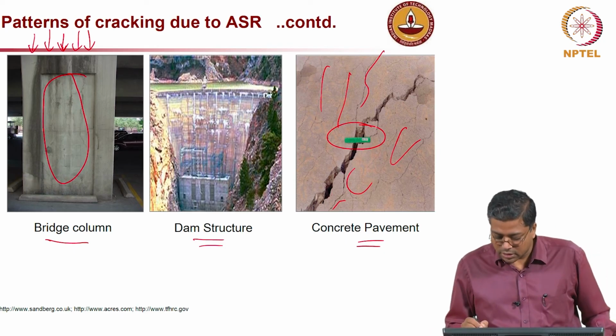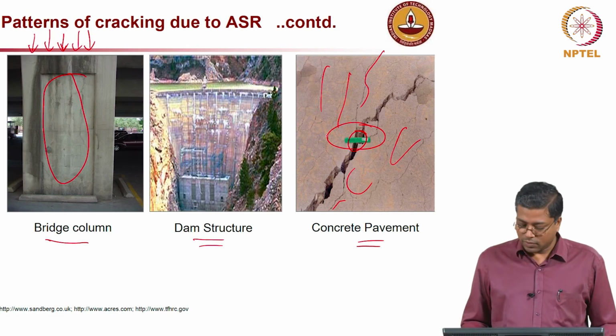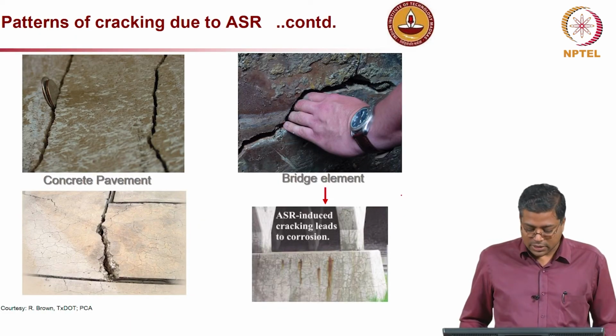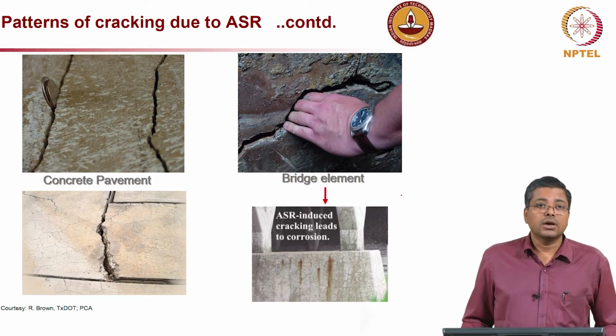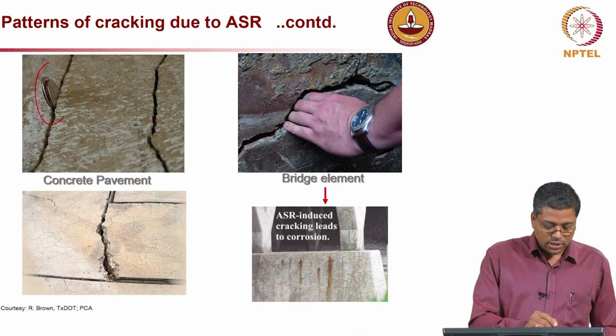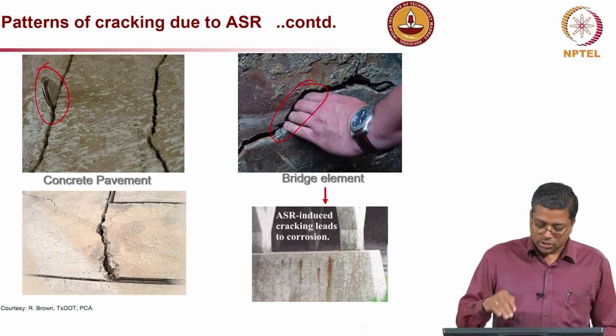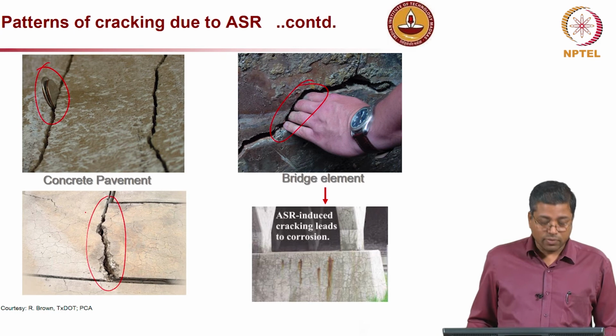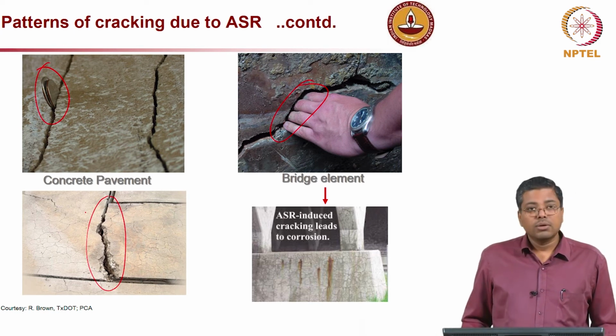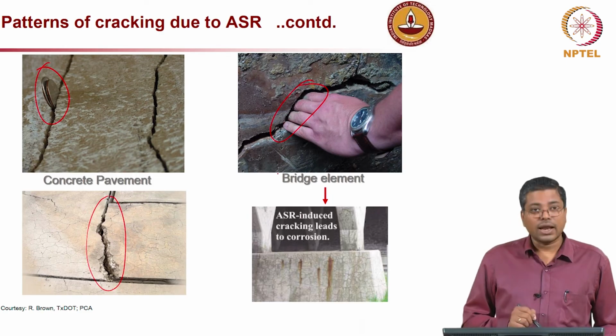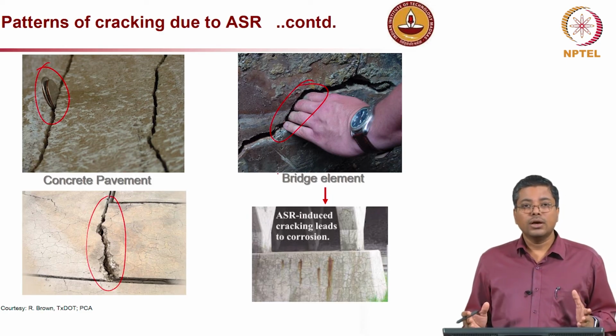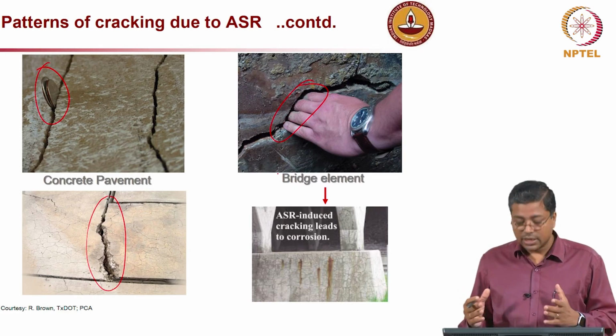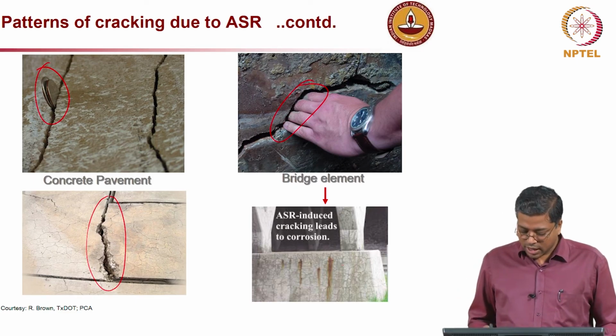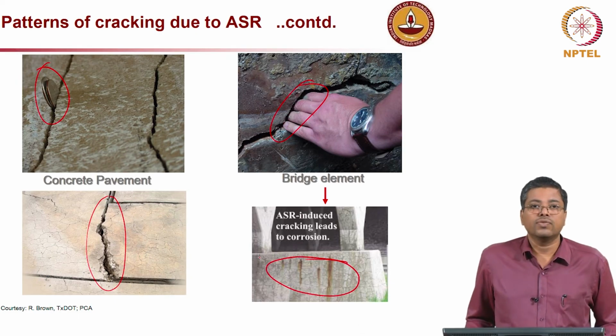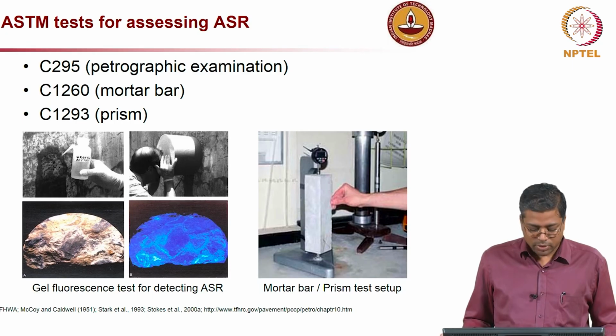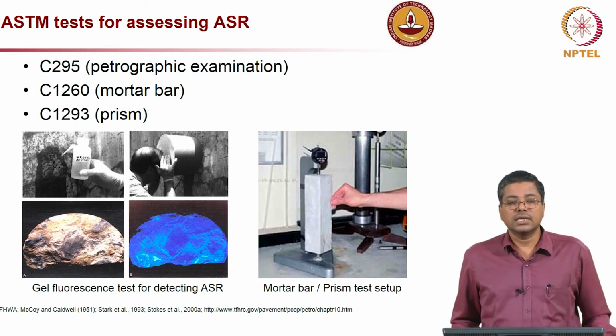You can see the width, this is at least about an inch wide crack, and these are additional examples showing how significant this cracking can be. On the left you can see a coin, and then fingers inserted into the crack, and also significantly wide cracks on slab elements. The main point is all these cracks will help other deleterious elements to enter the concrete and eventually lead to corrosion of the reinforcement inside, which is a big problem later. Now, how do we test for assessing ASR?